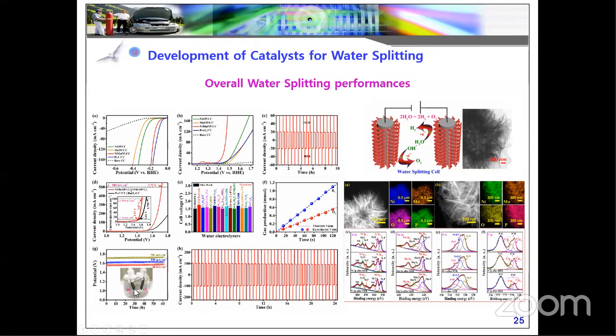So in order to prove the catalyst is more stable, we need to take the OER and HER electrodes. Here, on the oxygen generation side, the electrode is easily oxidized, and the hydrogen part may be reduced. So in order to prove it is stable towards the bifunctional activities, we need to take the HER side electrode and the OER side electrode. That's why we also evaluate the HER side and OER side electrodes, because both are the same electrode. Even though this is a device, we need to confirm both electrode materials are stable.